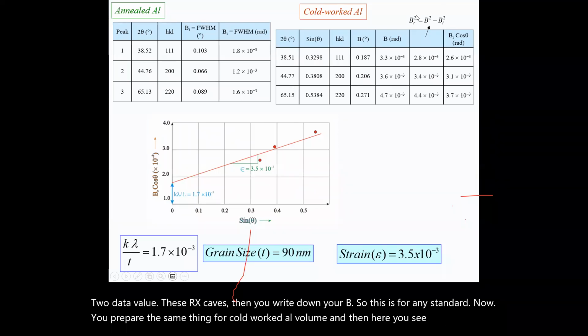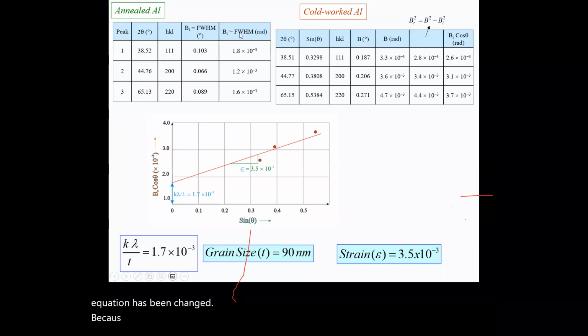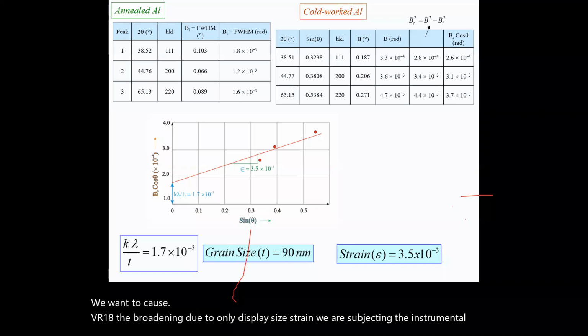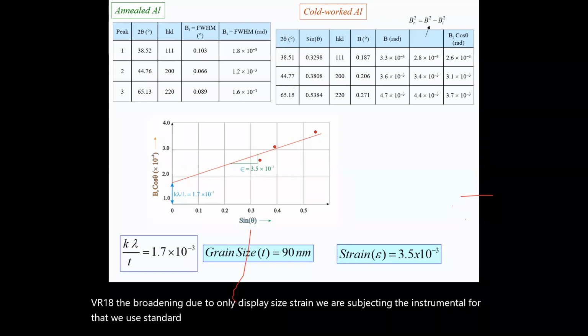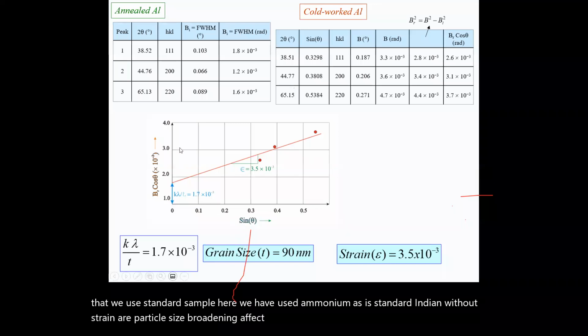the broadening equation has been changed because the BI is standard. Okay, we want, because we are taking the broadening due to only crystallite size and strain, we are subtracting the instrumental broadening. For that, we use a standard sample. Here, we have used aluminum as a standard. Annealed aluminum is without strain and particle size broadening effect. Then you plot this, and then finally you have this crystalline size and strain. So this is a general example which we are doing.